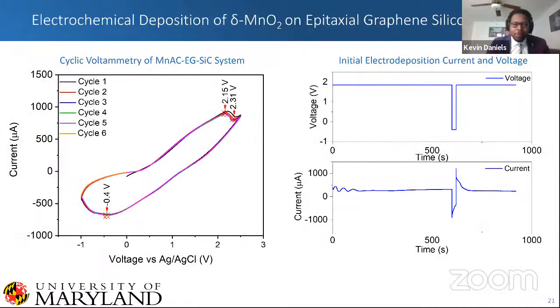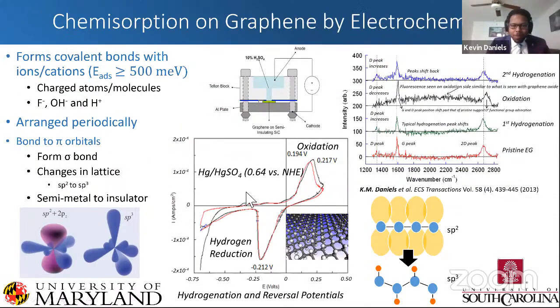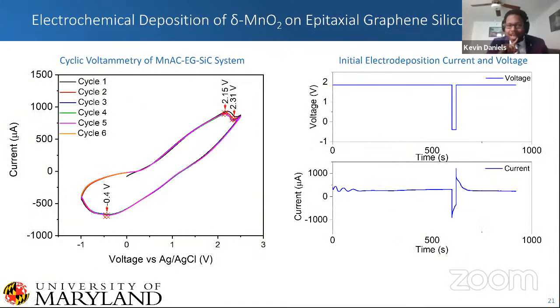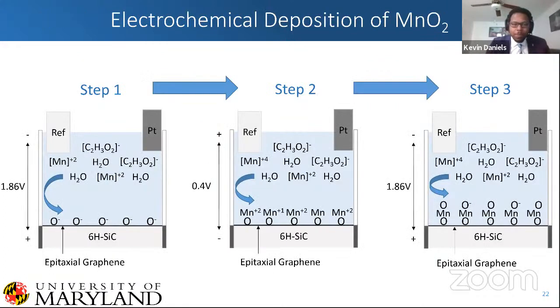So we did the cyclic voltammetry, like we did in the previous one, where we cycled the potential to see the redox potentials in the solution. Here we use manganese acetate as our manganese source. We cycled the potential, and we were able to get these potentials at which manganese goes on at minus 0.4 volts, and hydrogen goes on, or excuse me, oxygen goes on over 2 volts. Okay, so we're able to do this electrochemistry.